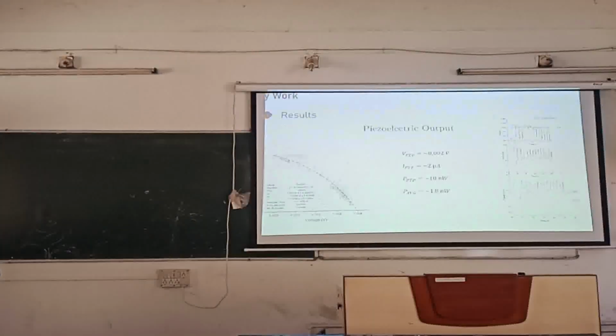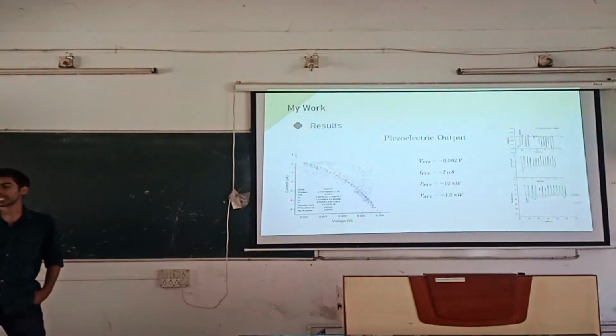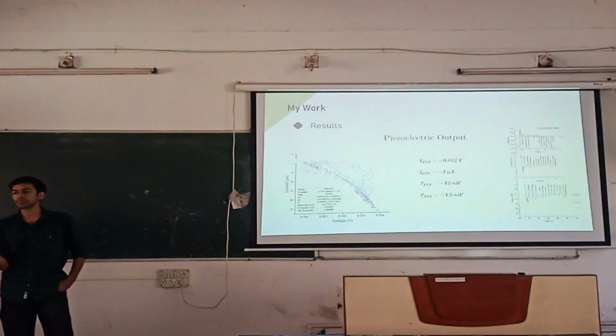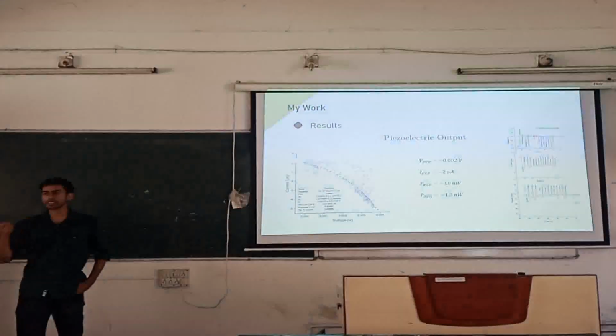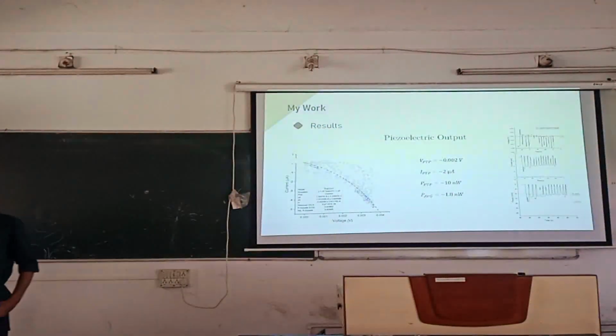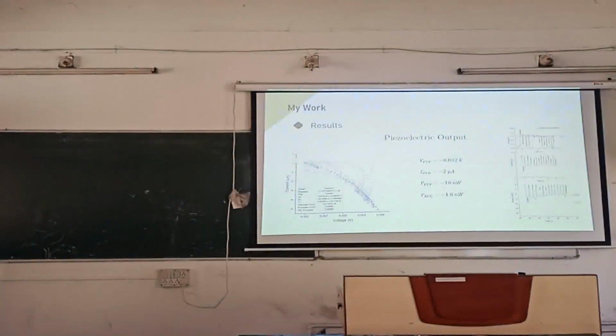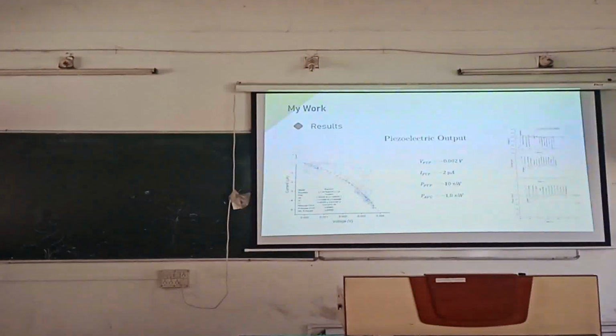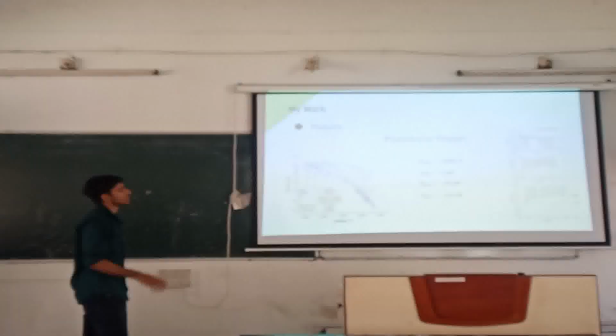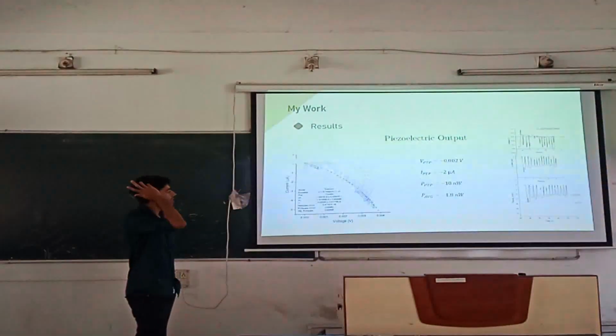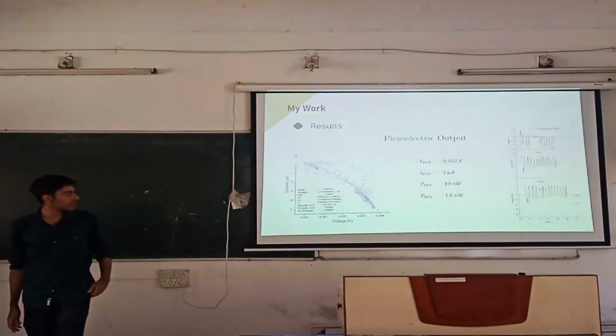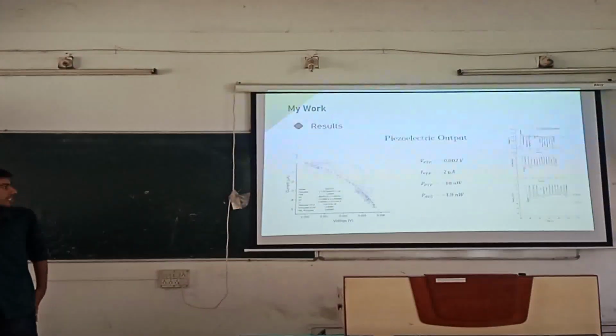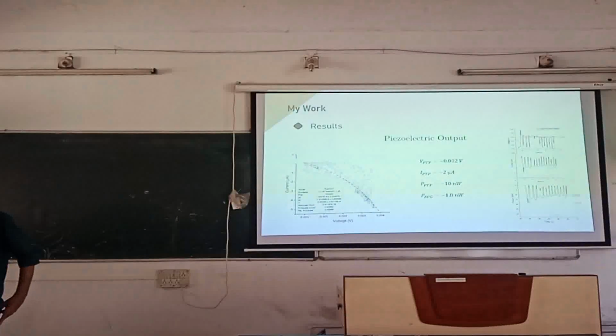And one more thing, this was totally based on the piezoelectric effect. We couldn't use the flexoelectric effect because we didn't have that zigzag electrode. So by incorporating both, we should be getting a higher voltage. But right now we got a peak-to-peak voltage of 0.002 volt, 2 picoamps of current, and a peak-to-peak 10 nanowatts of power.